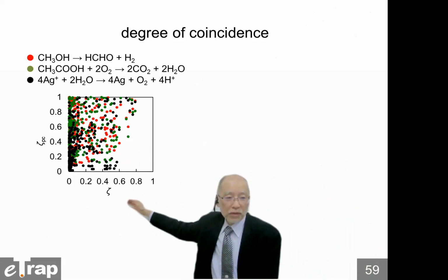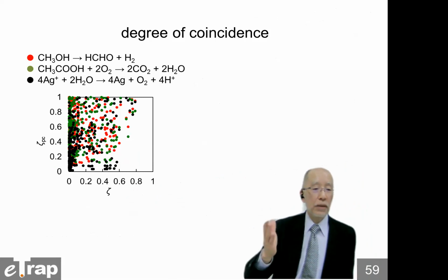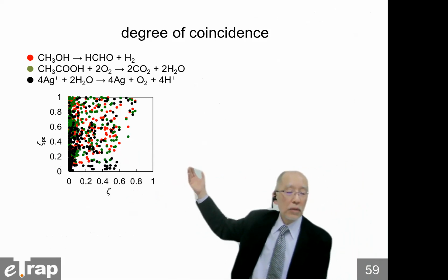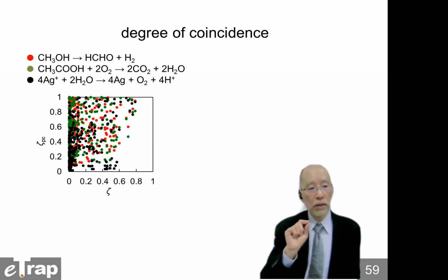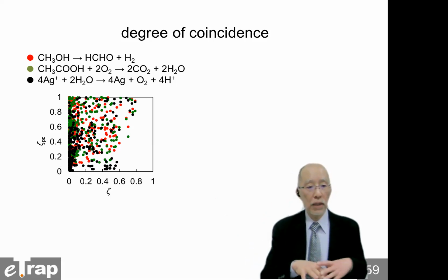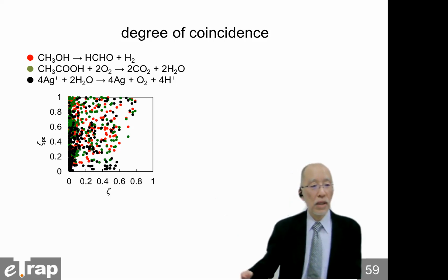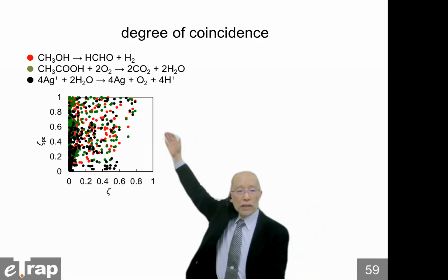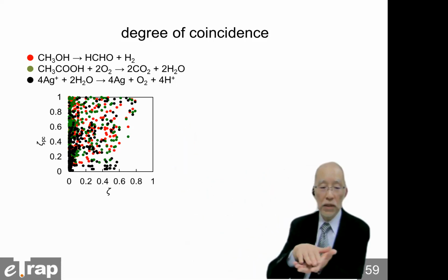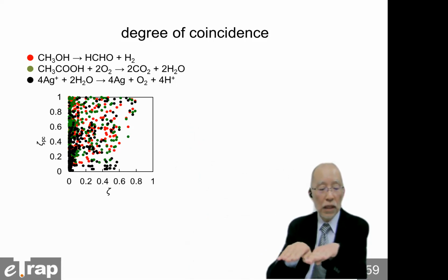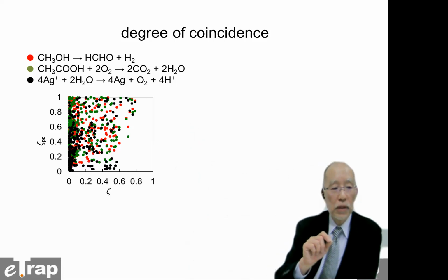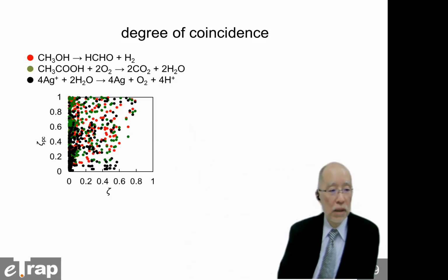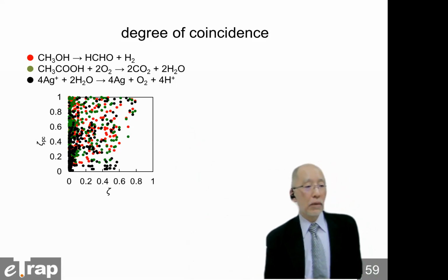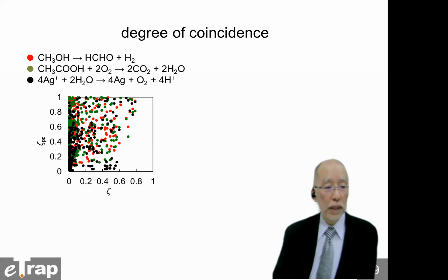To make it clear, the degree of coincidence of photocatalytic activity is plotted against the degree of coincidence for pairs of titanium oxide samples. And the red circle gives the degree of coincidence of photocatalytic activity for methanol dehydrogenation, producing hydrogen from an aqueous solution of methanol. And 1 means the activity is the same. That is not an absolute value, just comparing 2 titanium oxide photocatalysts for hydrogen evolution. The green one is carbon dioxide production by decomposition of acetic acid. And the black circles are the degree of coincidence of photocatalytic activity for the oxygen evolution reaction.